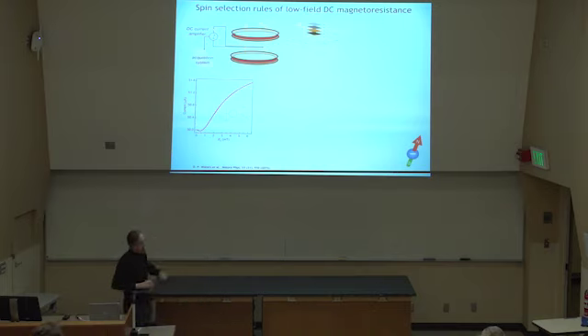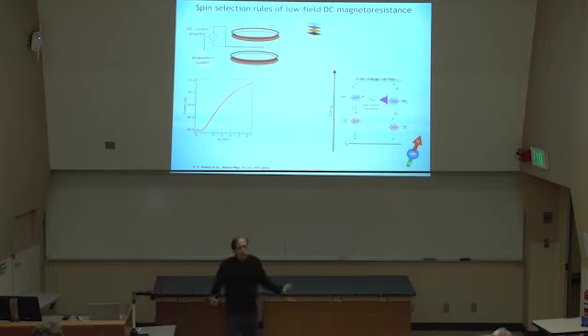And so, again, that's my standard example for a spin selection rule. People have studied decades to study this, and what actually happens is because of the injection of charge carriers, your whole device is in a non-equilibrium. That means, however, it is of course in a steady state, and under these steady state conditions, you have a constant recombination rate, which has a significant fraction of your overall current. And the recombination pathway illustrated here by this sketch, again, people put decades into this to figure this out. This is a two-particle picture that represents this.